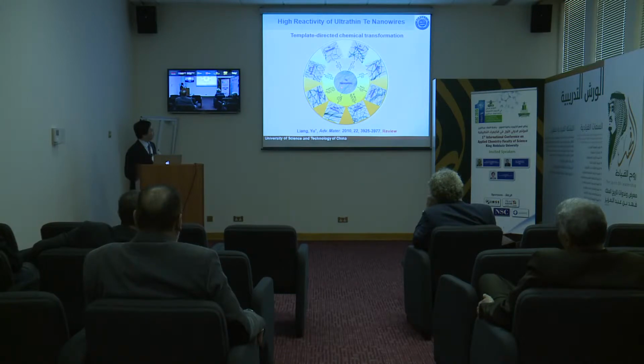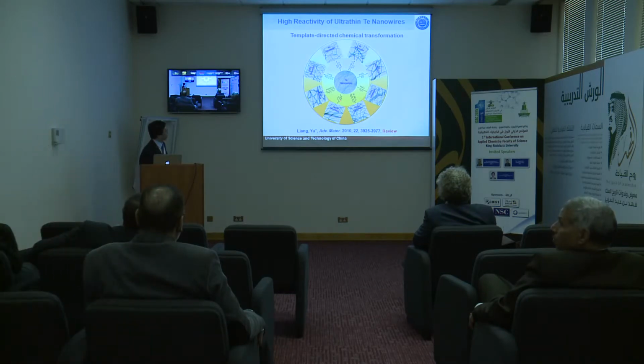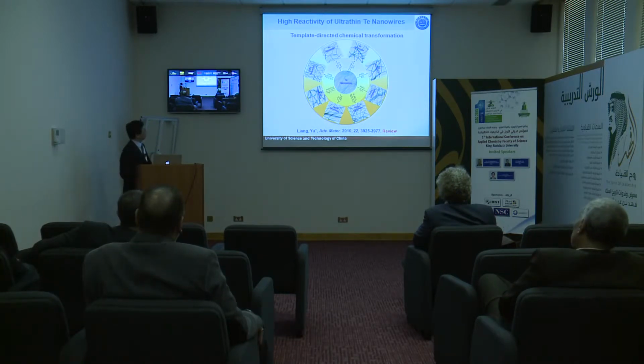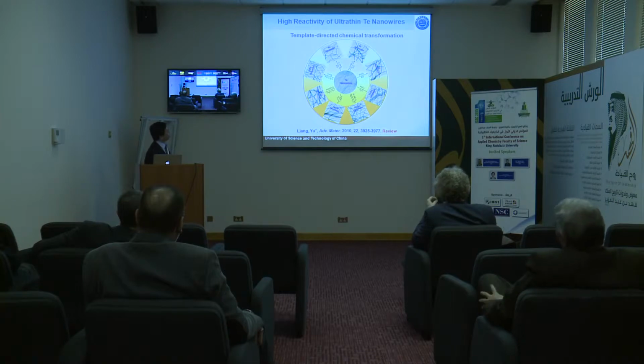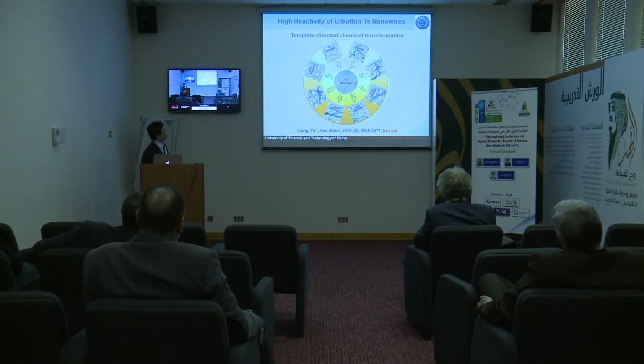Because these tellurium nanowires are very reactive, they can react with many metal species, ionic metal species. For example, if they meet cadmium chloride, they can chemically transfer into cadmium telluride nanowires. This is a topological transformation process, right? If you mix with silver nitrate, you will see it can chemically transfer into silver telluride. If you mix with other ionic metal species, then they can chemically transfer into semiconductor nanowires. You can do many things. You can even mix with gold acid or palladium chloride. You can transfer them into palladium nanowires or nanotubes. Many different systems you can try.